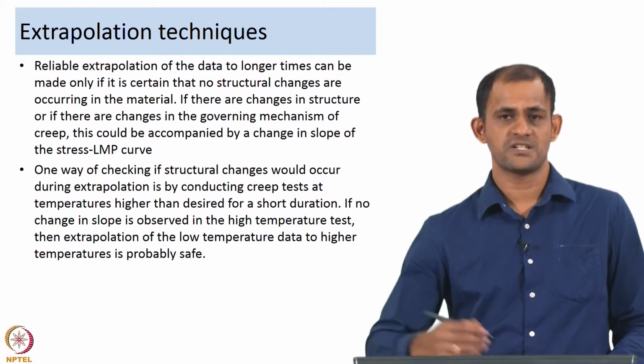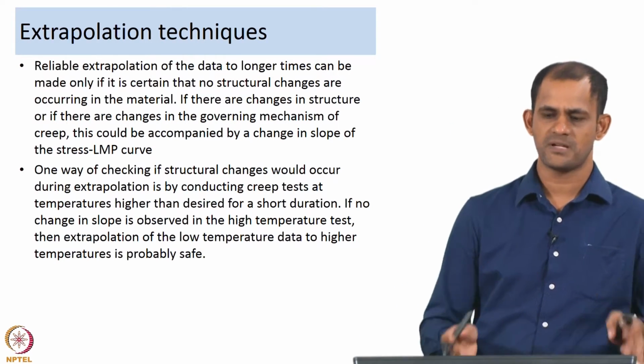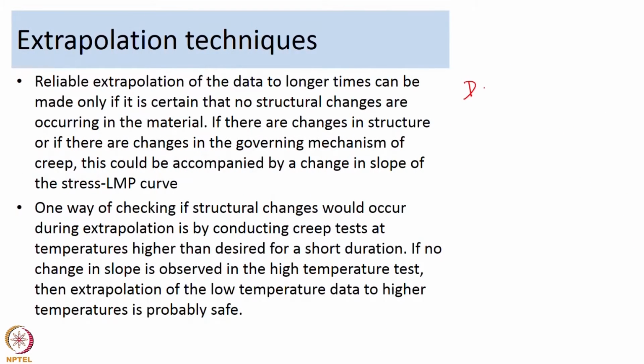Also, if there is a change in the governing mechanism of creep, for example, for a certain combination of time and temperature the mechanism of creep is diffusion controlled, and at another combination of time and temperature the mechanism of creep is dislocation controlled, then you cannot be sure about your extrapolation. You cannot carry out blind extrapolation without accounting for this change in deformation mechanism.